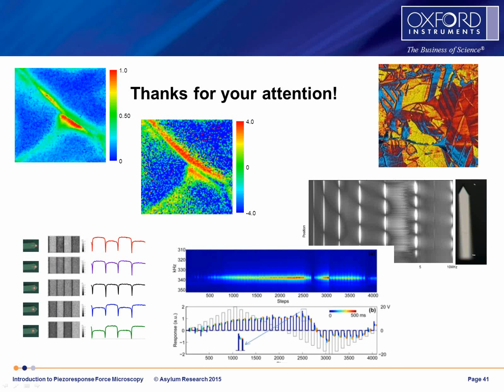Practically, however, we can separate them based on the time response. The ions moving in the lattice have very characteristic diffusion coefficients, so they move slowly. The ferroelectric polarization response is much faster. It's sort of sub-nanosecond regime. So in principle, if we can measure the response as a function of frequency, we can differentiate the ionic and ferroelectric component. Practically, of course, once we do these measurements, our material response is convoluted with the transfer function of the cantilever. So you will primarily see the cantilever dynamics, not the ion dynamics. Until very recently, that was theoretically doable, but practically not. Now, with the advent of these interferometric methods and cantilever transfer function measurement methods, that probably becomes possible, but it's a matter of the future.